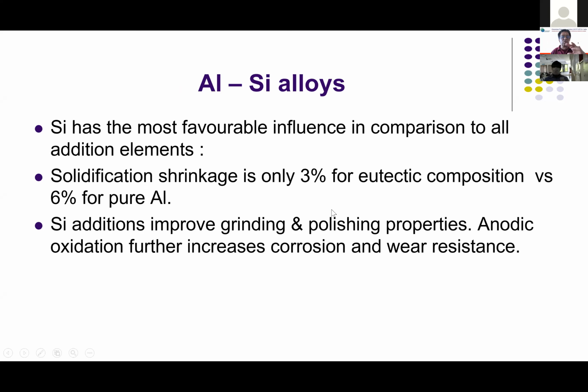Okay, coming back to aluminum silicon alloy, solidification shrinkage is only 3% for eutectic composition versus 6% for pure aluminum. Solidification contraction is about 6%, whereas when you add silicon and make an alloy, the solidification contraction is 3%. That means it is easy to cast, especially in gravity and low pressure.